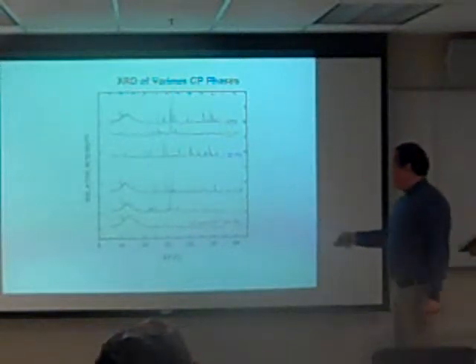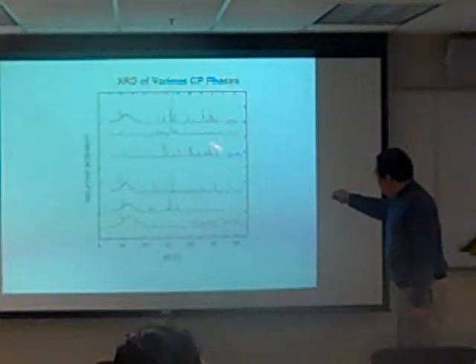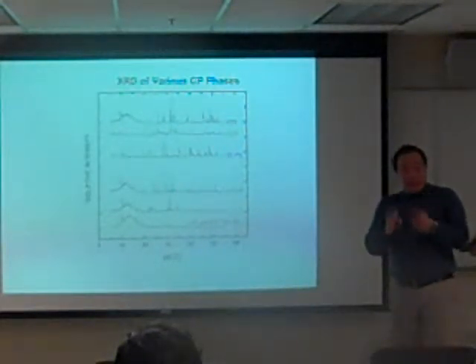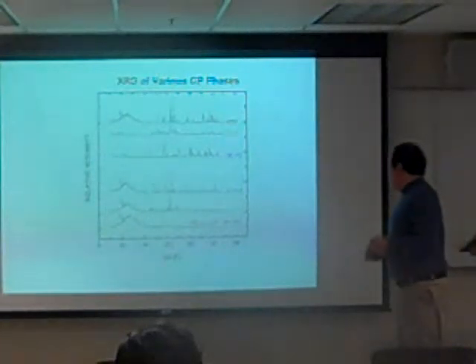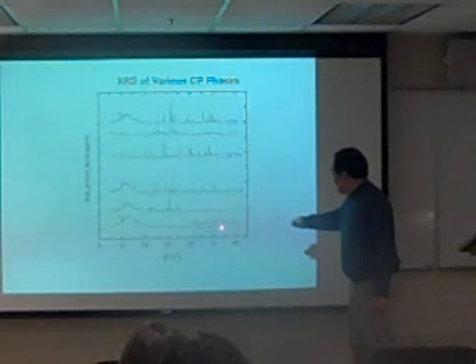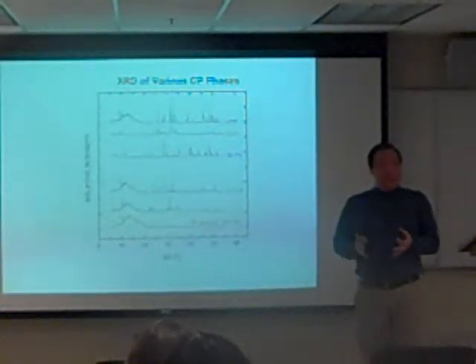Now, one obvious way of doing it is X-ray diffraction. Of course, you can have these characteristic peaks from the X-ray diffraction pattern, but what happens if you have a very small amount of material? So let's say we have 15 micromoles per square meter of calcium phosphate. That's basically at the onset of nucleation and growth. How do we analyze things that small to be able to characterize the phase?